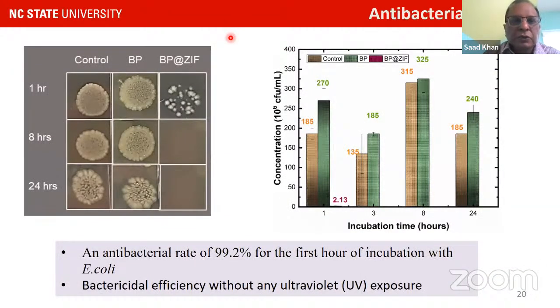The other thing we can do is look at antibacterial efficiency. So here is a control, and you can see when we grow E. coli, it seems to grow. And even with banana paper, it seems to grow, but when you have banana paper MOF, within an hour you actually start disintegrating or killing the bacteria.